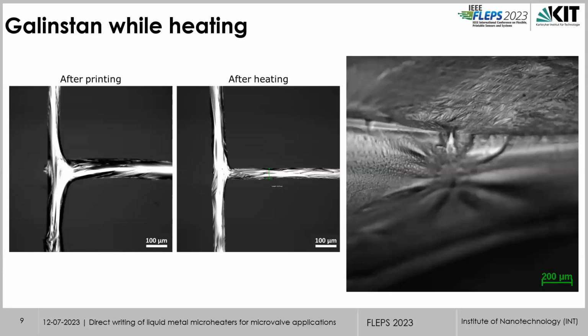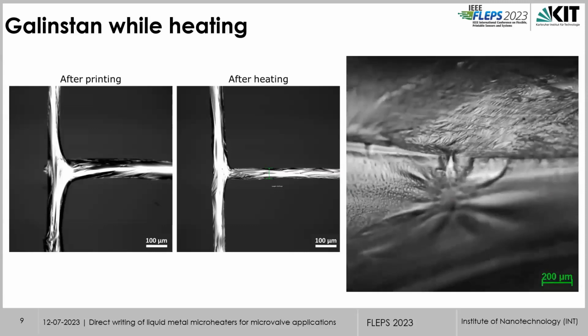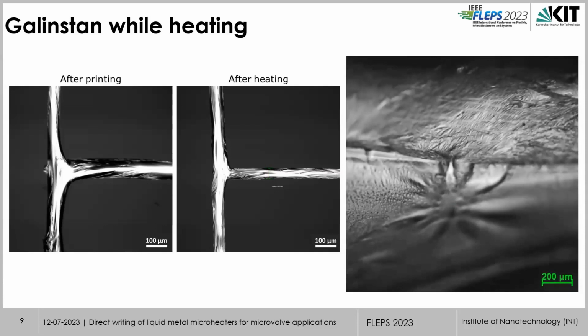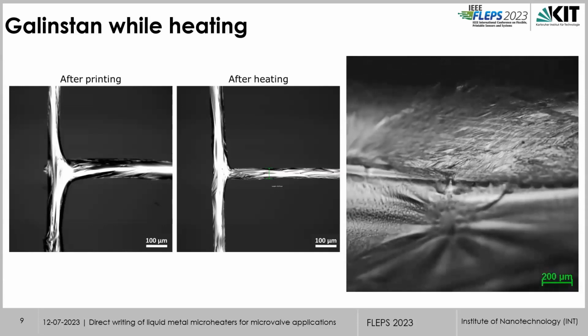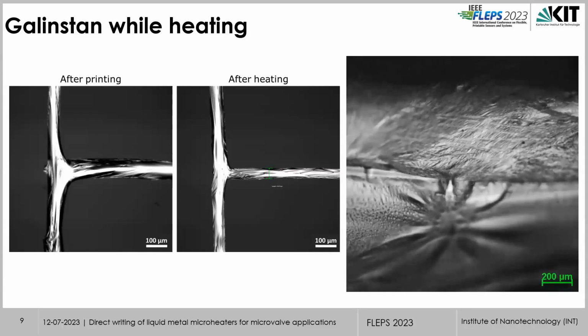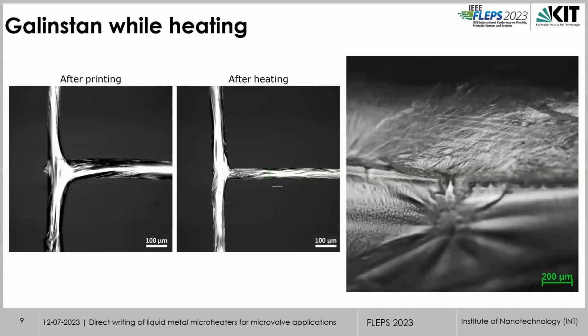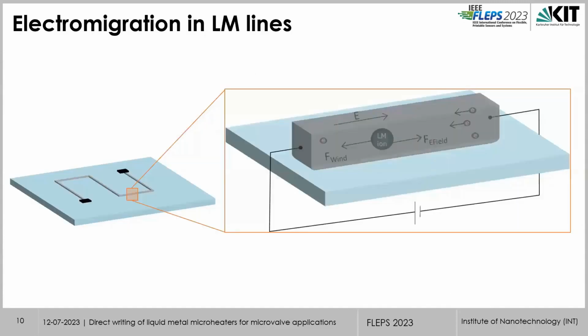And if we see it under the microscope in the video, we see that when the bias was applied on this liquid metal line, there is something going on in the liquid metal lines. Also, after applying bias, when the liquid metal microheaters heat up to more than 40, it becomes highly resistive, or even causes complete failure of the circuit. That might be because of electromigration in liquid metal lines.